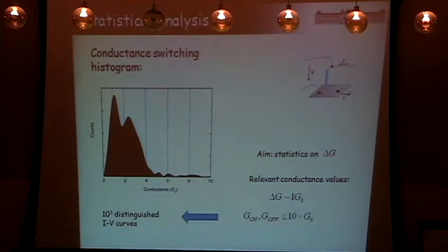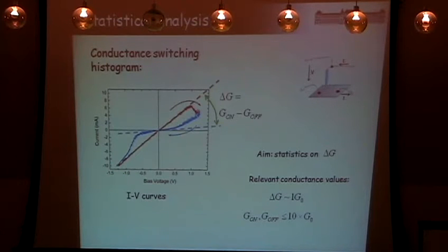Because if you go back to the hysteresis curve we were showing... this one? So yeah, you have one ball there, and you have lots of heating. So you may actually have a motion of atoms because of heating. Yeah, but I mean, heating itself is not necessarily enough because this is clearly an asymmetric curve. If it's only attributed to heating, then it should be symmetric. Sure, but it is something that you may actually consider, because heating, especially of one ball, is substantial.